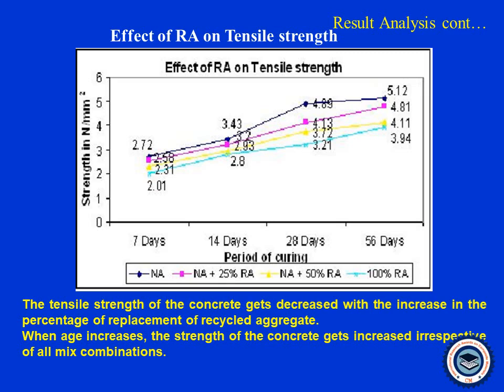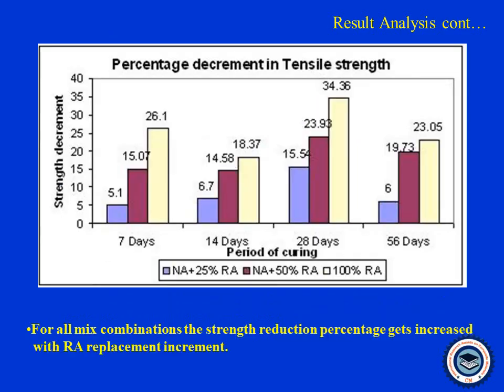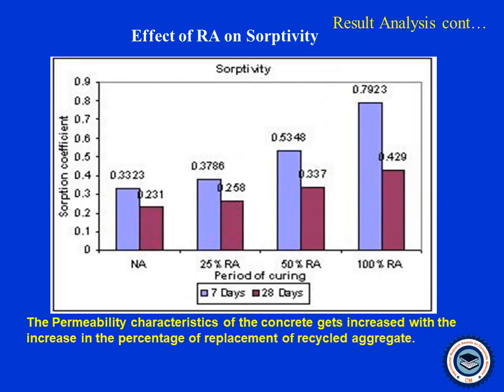So from the results, it was very clear that the recycled aggregate could be used as a structural concrete with some modifications in the mix design. It would also depend on the size, distribution, interconnectivity, shape and tortuosity of the pores, etc. In recycled aggregate concrete, the increment may be due to increase in the water absorption capacity of recycled aggregate because of existing mortar adhered even after the cleaning.